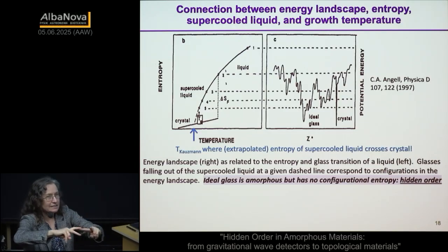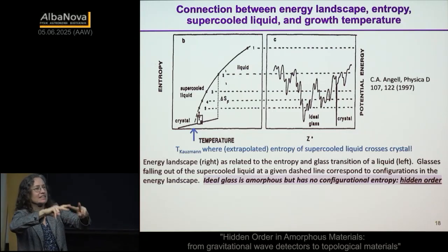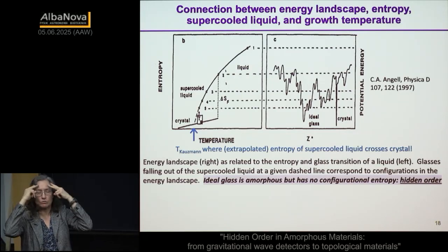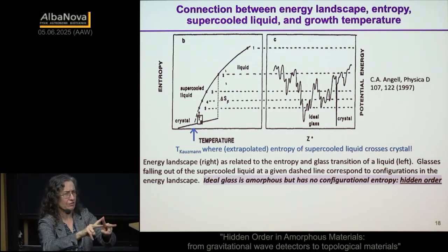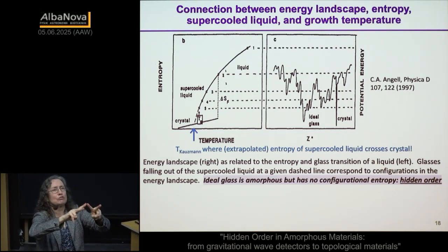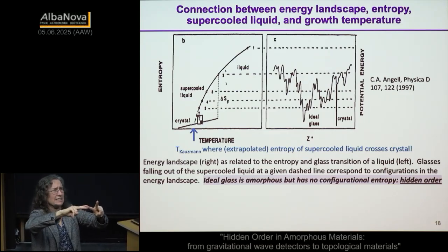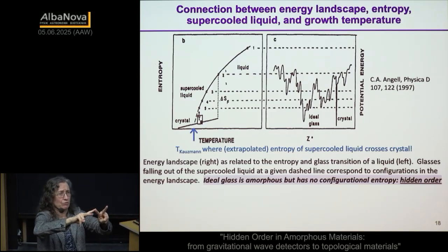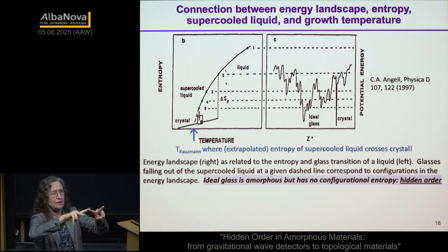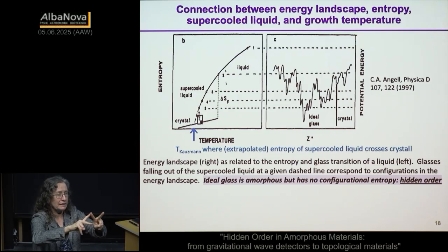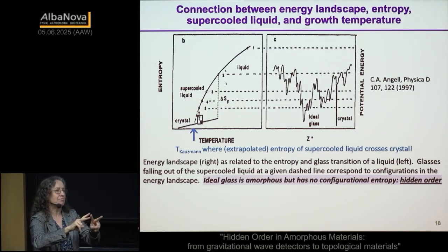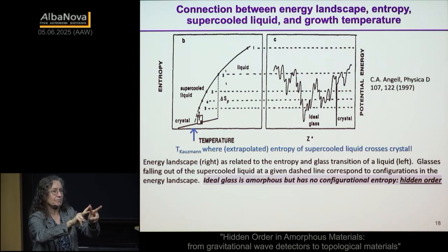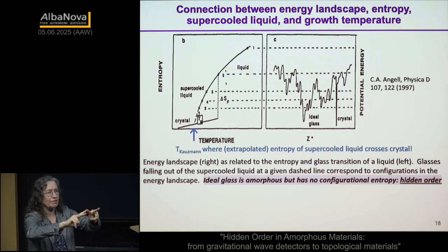And that is the reason that crystalline silica has about a zillion, what's the word that I want? The allotropes. Do I mean allotropes? I think I mean allotropes. All the different crystal structures. So crystalline silica has like 10 different structures it can form, which are all about that flop. This angle never varies, but that angle can vary all over the place. So obviously, in the amorphous structure, that is going to have much more degeneracy because I can make that angle vary a lot.